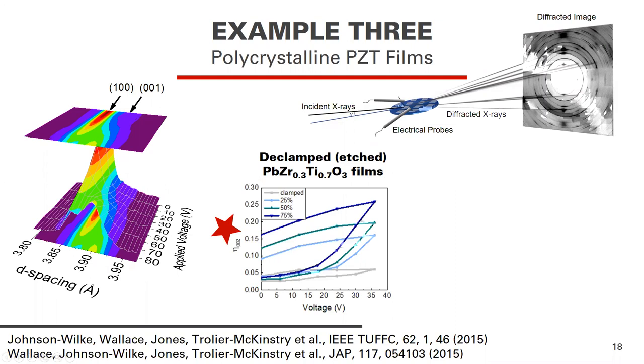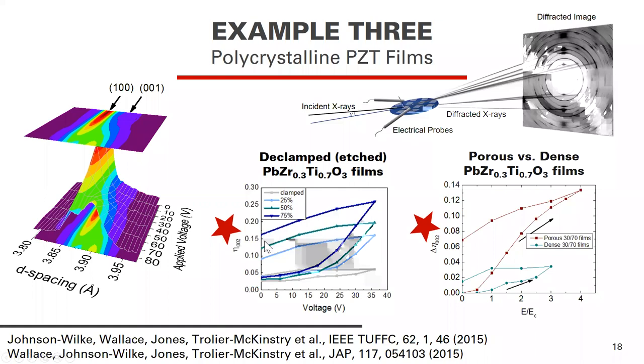Shown here first are samples that are mechanically declamped through etching. And if we use this indicator, eta, as a metric to describe how much domain switching we have as a function of voltage, you can see that as the degree of declamping increases up to 75% declamped, we're allowing more domain reorientation. So hopefully that demonstrates the value of this to thin films. We also investigated porous and dense PZT thin films, and you can see that the purposeful introduction of porosity also allows you to substantially increase the degree of domain switching that you're seeing.